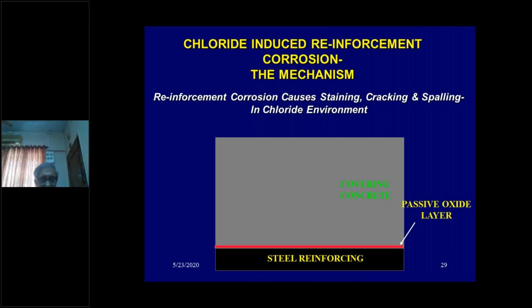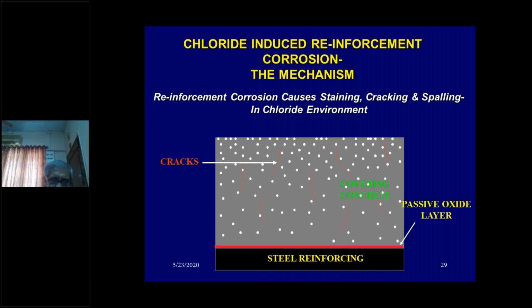There is a nice model made. You can see there is a passivating layer which does not allow the reinforcement steel inside the concrete to corrode. Even though there are minor cracks, they are all isolated, but when the chloride and water start seeping in, the cracks unite and pass on the water to the bars, and then you can see flaws, reinforcement passivation is lost, and corrosion happens.